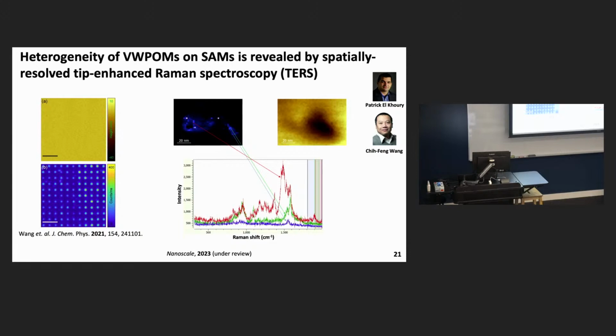where you just push the tip into the surface. And this gives you high aspect ratio features which enhance the electric field and also the Raman spectra that you see resulting from it. So here is a close-up of a single defect and spectra taken at 3 different points. And you can see that even on a surface that's prepared under such well-defined conditions, you still have substantial differences in the spectra, meaning the interaction with the surface is highly dependent on whether there are local defects or changes in the curvature of that self-assembled monolayer.